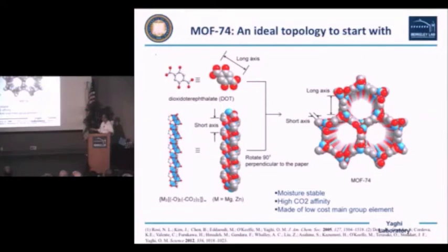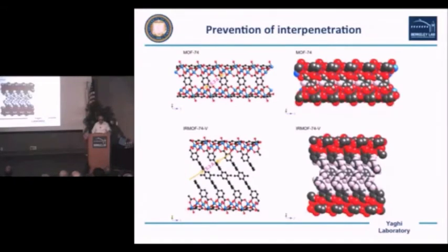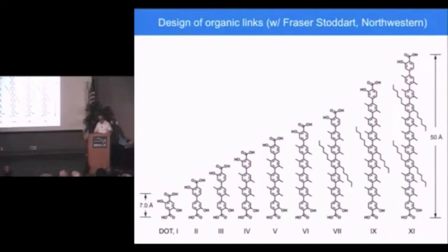This could be zinc oxide or magnesium oxide, and the rods, again here pointing into the screen, are linked by organic units, in this case this phenylene unit. It turns out this is one of the stars for hydrogen storage and has really very interesting carbon dioxide capture properties, but it does not interpenetrate, and so it was a nice structure to expand its pores.